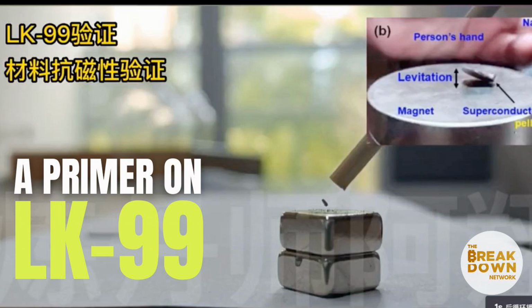Now, another problem with the process is that it creates extremely low yields. The claimed successful replications out of China have produced samples no larger than a grain of sand. The chemistry involves a good deal of luck to be successful. During the process, copper atoms replace lead atoms within the material structure, which happens entirely by chance. To create a viable sample, this luck has to occur within a continuous chain of atoms to create a superconductor large enough to test. Adding to the problems, LK-99 is only a superconductor along one dimension within its three-dimensional structure. This means that some samples may not levitate, making them much harder to detect.